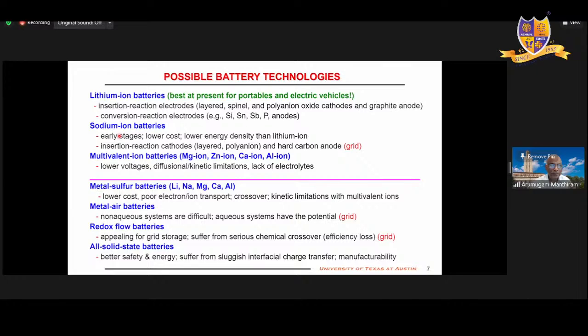Multivalent means magnesium 2 plus or aluminum 3 plus, very appealing because if I store one lithium or one sodium, I store only one charge. If I store one magnesium, one zinc or one calcium, I store 2 charges. Wonderful. If I store one aluminum, I will store 3 charges. So that means I am tripling the energy density from aluminum or doubling the energy density with magnesium and zinc compared to lithium or sodium. Wonderful. But